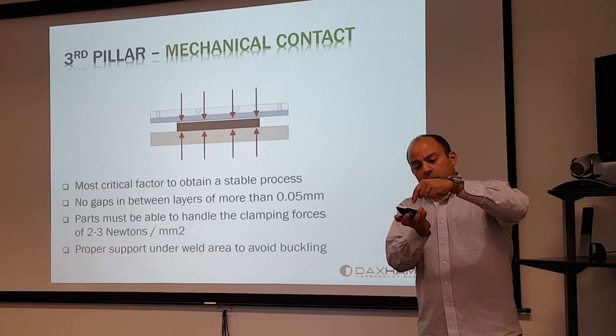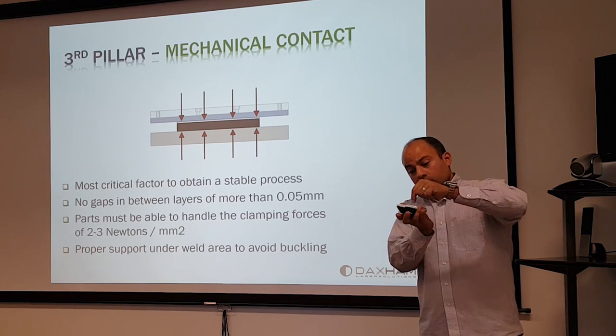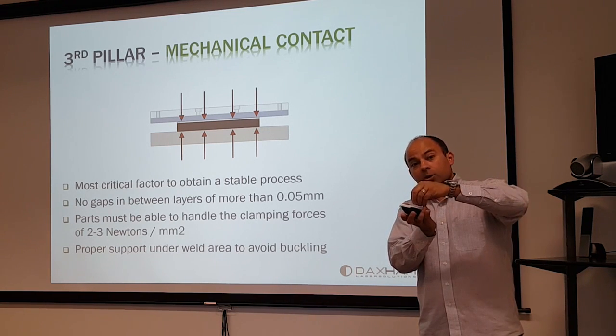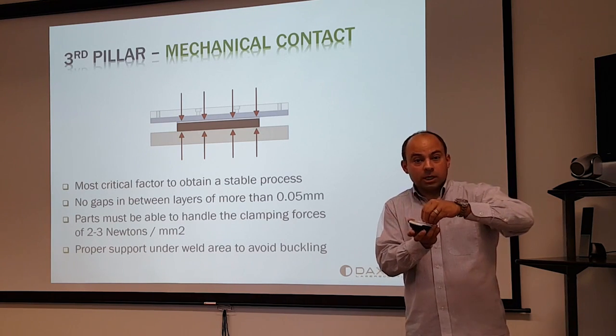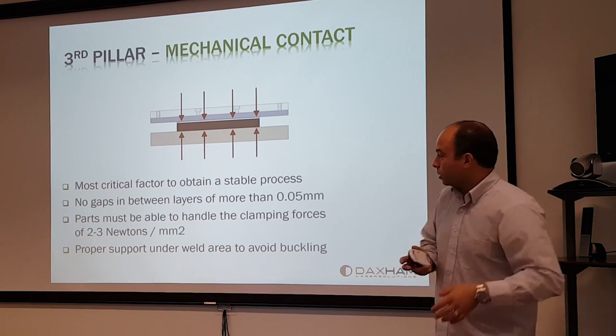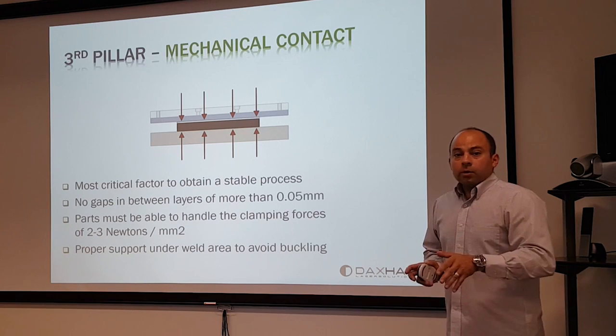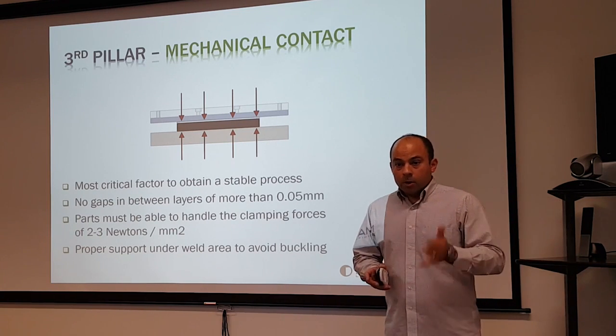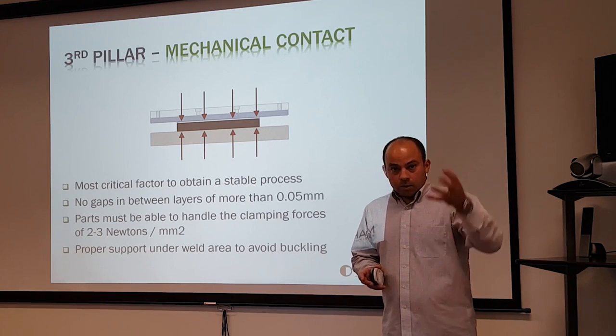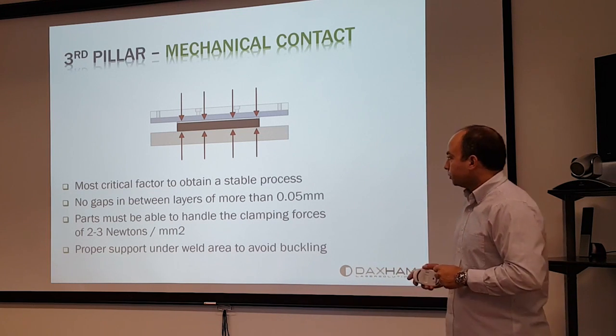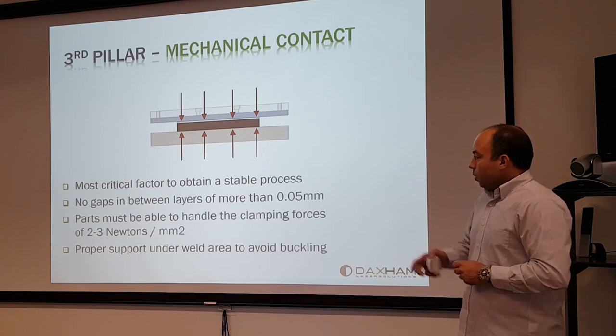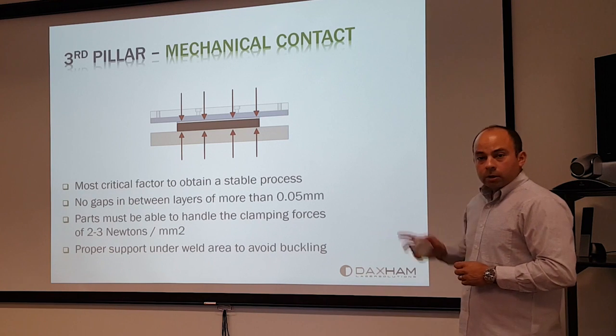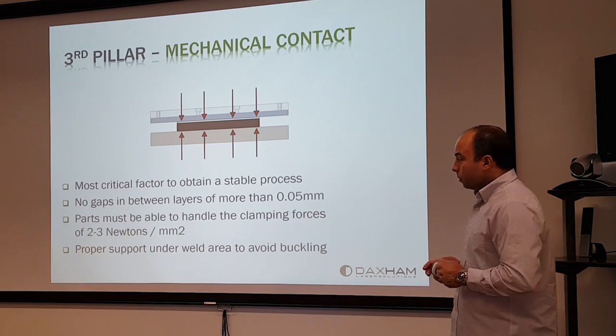What's going to happen is the laser is going to shine through the transparent layer, get absorbed into the lower layer, and burn and turn this lower layer to carbon before it can transfer the heat to the upper layer and get a stable process. Very, very, very critical that the clamping is designed right, no gaps, holds the part tight while the laser welds. Again, no gaps in between the layers of more than 0.05 millimeters.